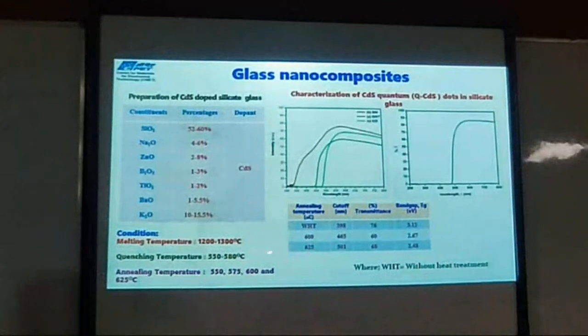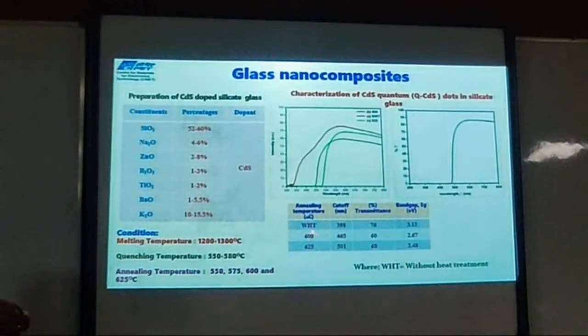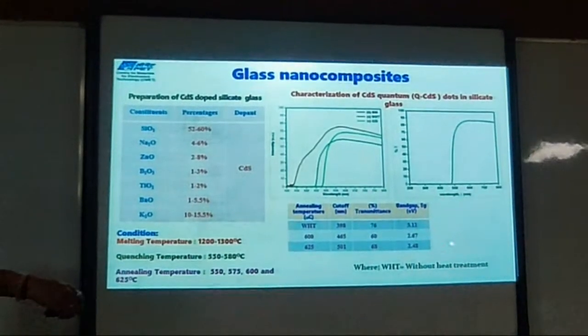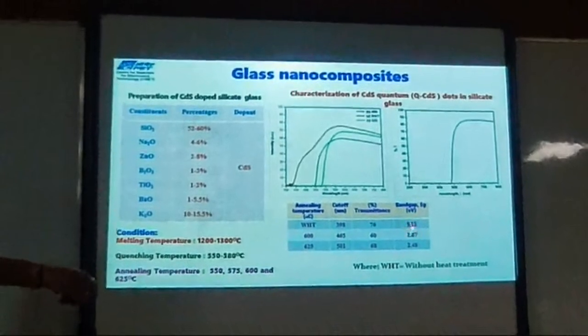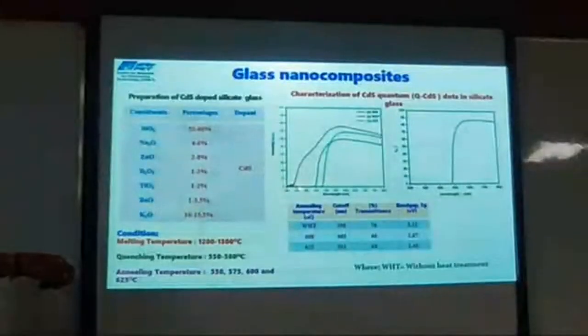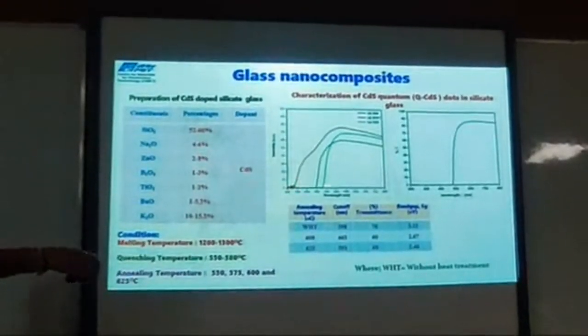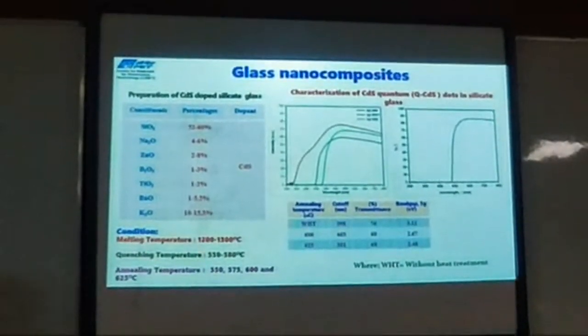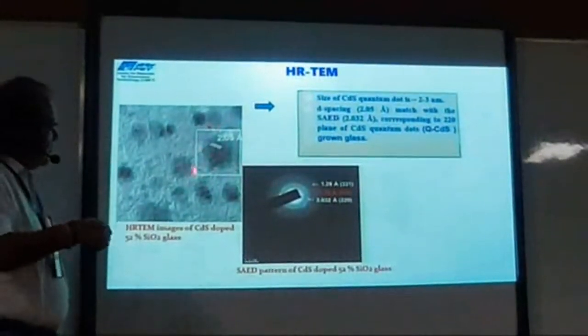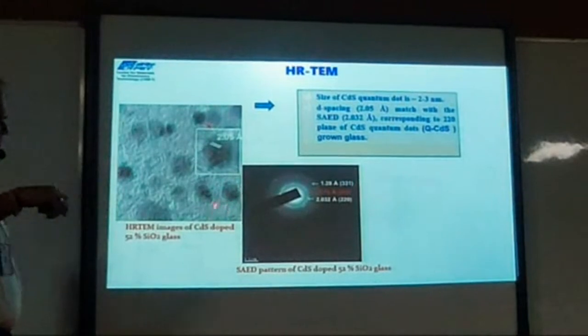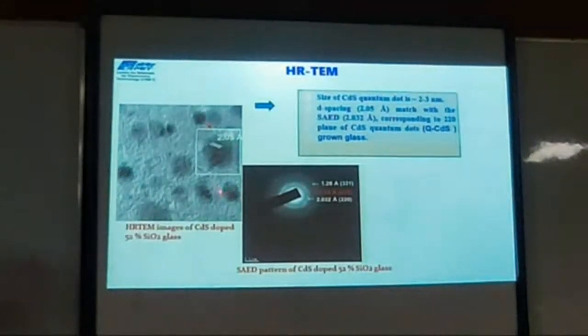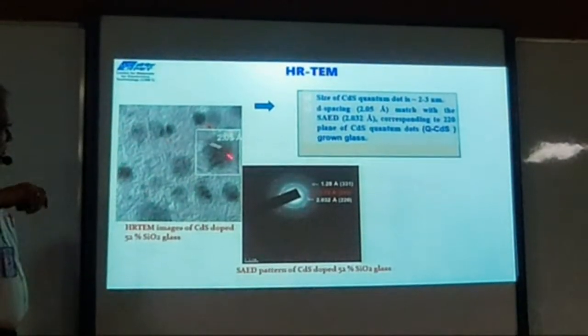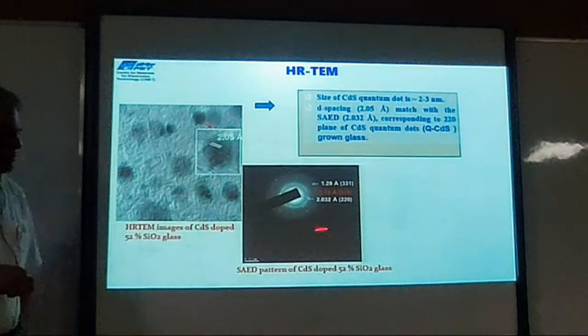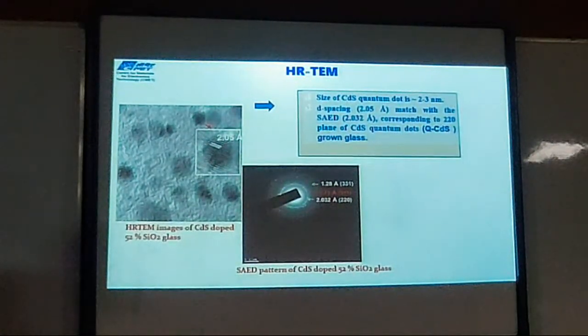There is a low thermal processing from 500 degrees to 625 degrees centigrade in a controlled manner, and we can see here we can grow cadmium sulfide. You can see the band gap can be changed: initially the absorption is in the UV region, and when you grow CdS, it goes to the visible region. So this kind of thing is very, very important in glasses. In the transmission electron microscopy, these isolated cadmium sulfide quantum dots are seen. They are only 2 to 3 nanometers, and they are uniformly dispersed in the glass. And the beauty of this is that they are polycrystalline, so you can see that highly crystalline particles can be grown in the glasses.